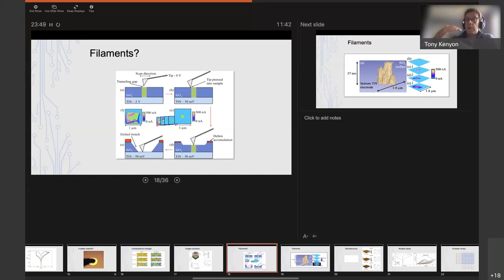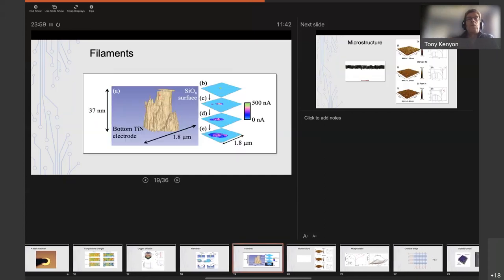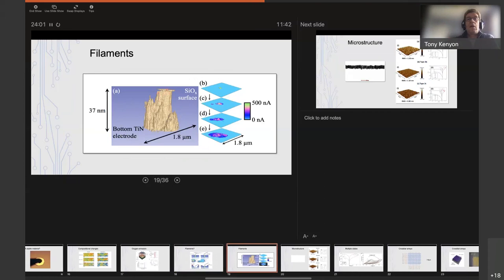And hopefully, if we can look for one of these filaments that's forming, and here it looks like we've seen the top of a filament, we can then profile it in three dimensions. And that's what we did, and this is what we see. We see in this case a filament here that connects the top electrode would be at the top here, bottom electrode at the bottom, and we can see a filament that's forming.